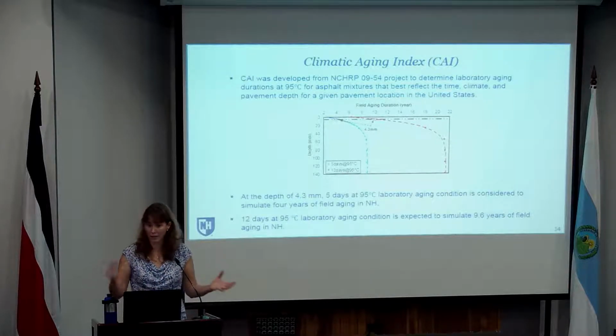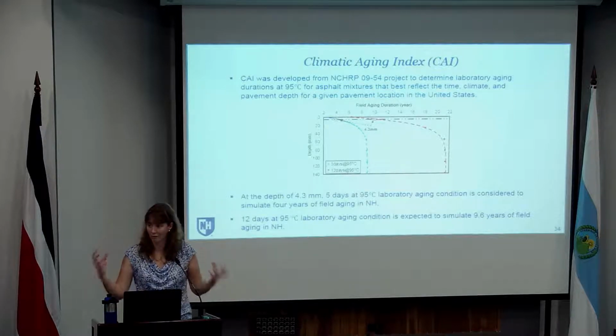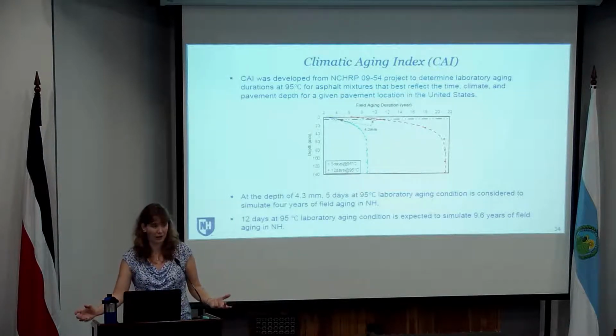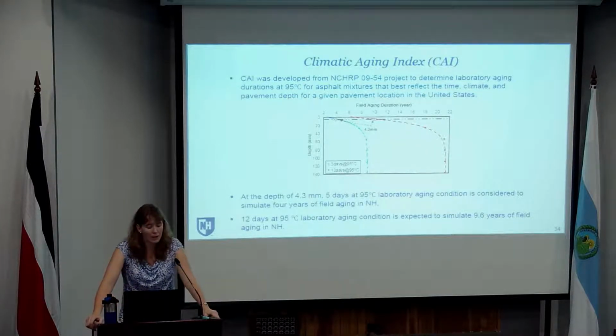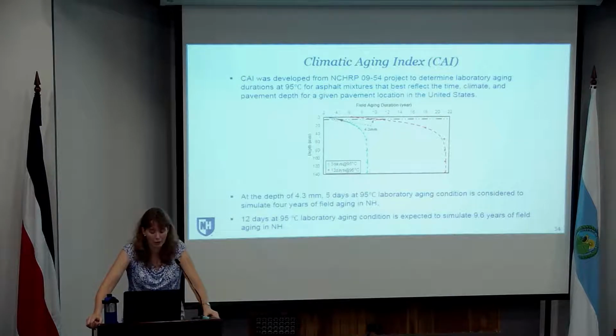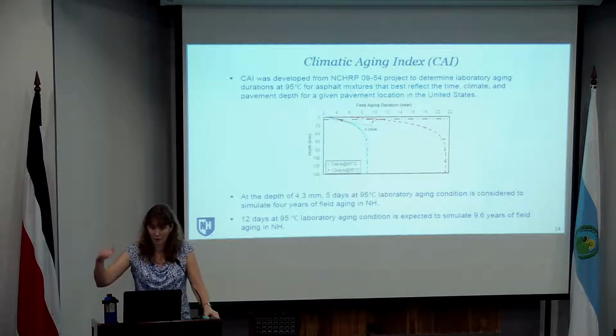Okay, so we know the time because we've got the cores from 4 years, but really what's that reflecting in terms of the depth according to this model that they developed and calibrated. It's a national calibration, but at least looking at comparatively where do we fall. So looking at this for the 5 days of aging, it looks like the appropriate depth that we're simulating is 4.3 millimeters in terms of depth from the surface.